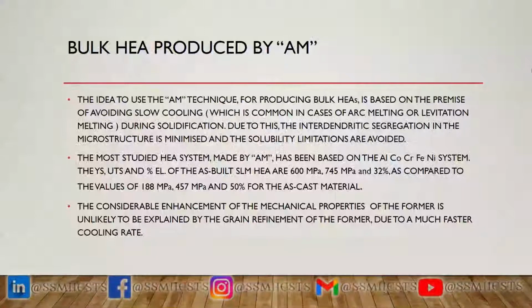Now, in addition to coatings, we also produce high entropy alloys in the bulk form. So the idea to use AM technique for producing bulk HEAs is based on the premise of avoiding slow cooling. You see, in the AM process, the biggest advantage is avoidance of slow cooling, which is common in case of arc melting or levitation melting during solidification. Due to this, the interdendritic segregation in the microstructure is minimized and the solubility limitations are avoided. So this is very interesting.